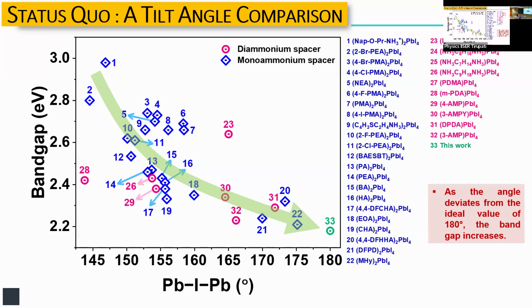Basically, with a 180 degrees angle, the electrons have the best probability of hopping from iodine to lead. And this ability to hop makes the bandwidth larger, which makes the band gap the smallest. And that's why you find the band gap the smallest. So with the model she chose, she managed to get this 180 degrees magic angle, which no one else had got. We also understand why that happens, but I'll not have time to go there today.